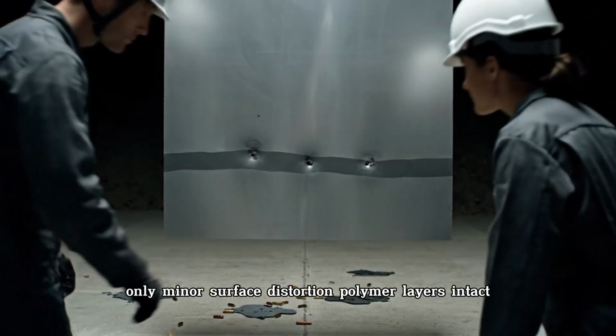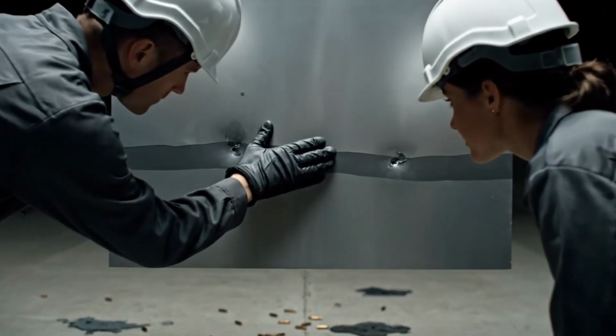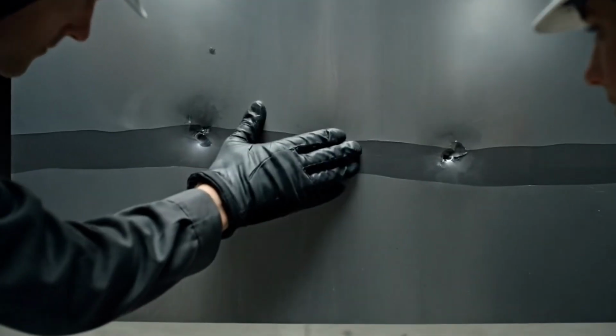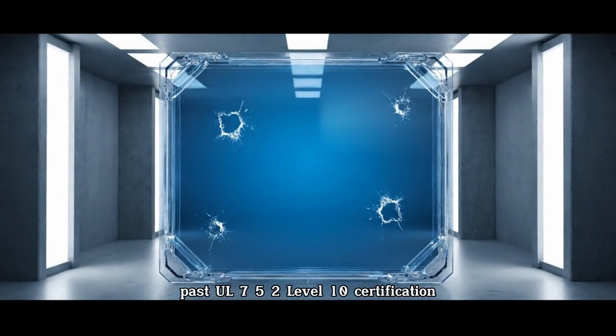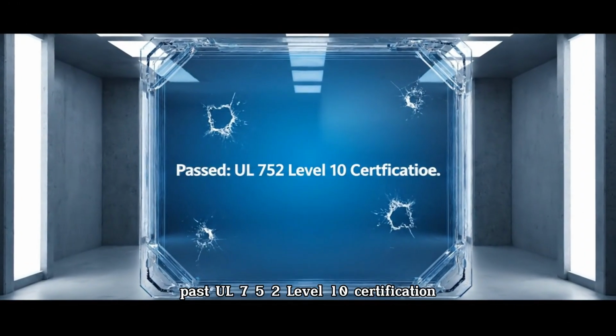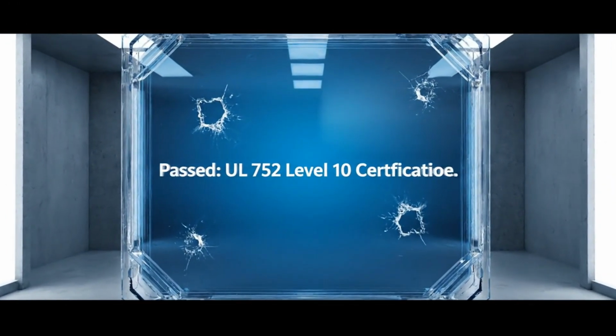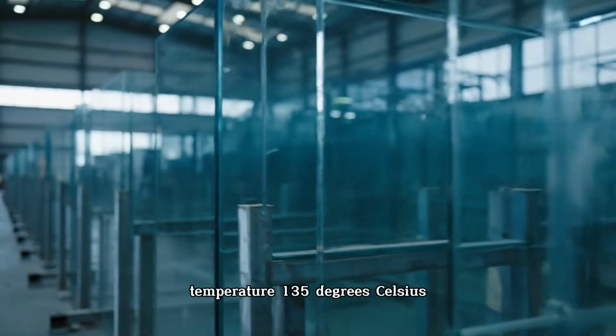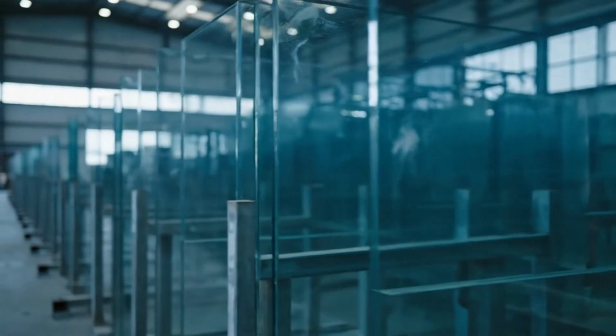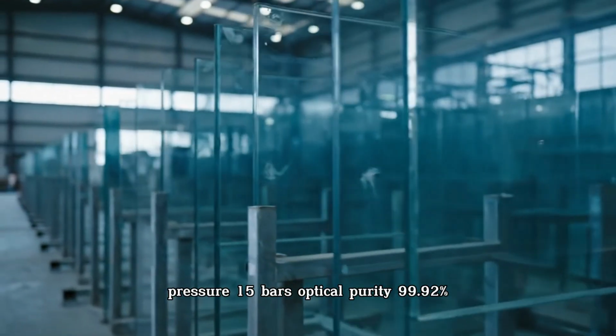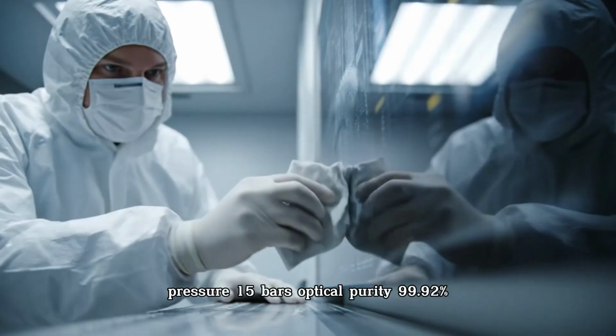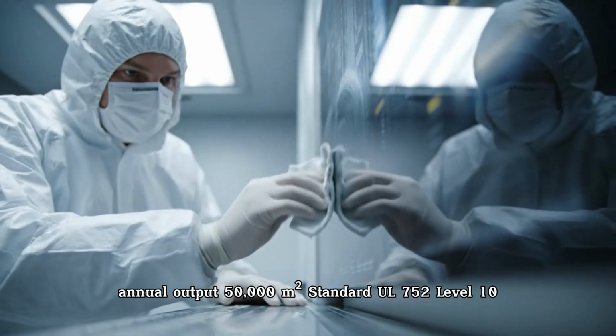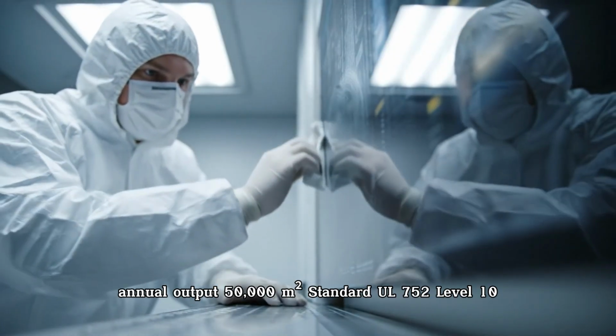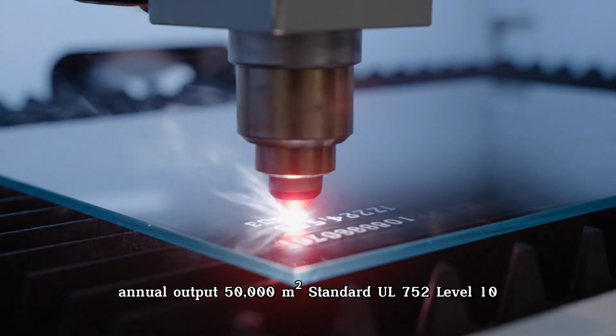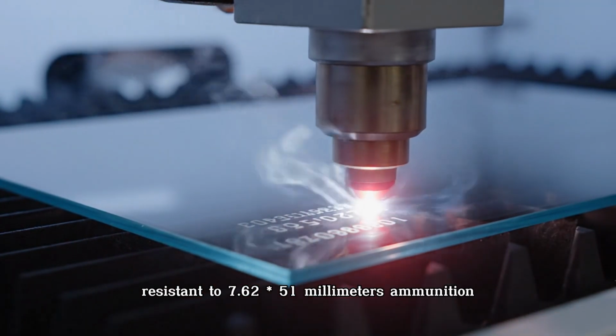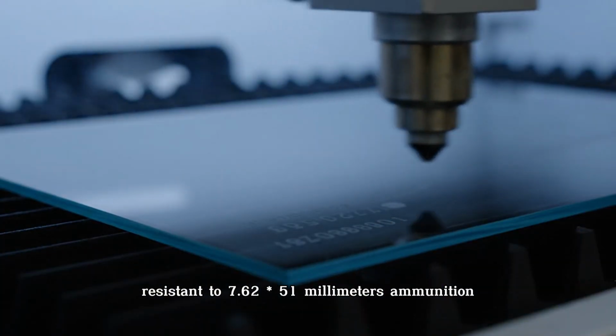Only minor surface distortion. Polymer layers intact. Passed. UL 752 Level 10 certification. Temperature, 135 degrees Celsius. Pressure, 15 bars. Optical purity, 99.92%. Annual output, 50,000 square meters. Standard, UL 752 Level 10, resistant to 7.62 times 51 millimeters ammunition.